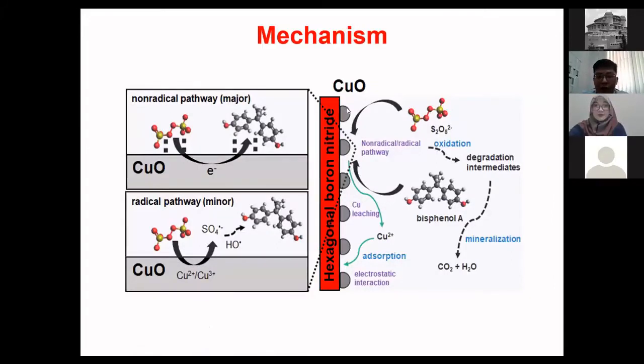You have the copper oxide, right? And then you have this support, boron nitride. And when you have activation process through non-radical and radical pathway, right? Then you have some reactive species generated to attack the pollutant. And what is interesting is that the copper leached out, right, will be reabsorbed back on the boron nitride. And after adsorption, you can take this catalyst, you calcine it at about 300 to 400 degrees Celsius, and then this adsorbed copper can turn back into copper oxide. So that means you are not losing any copper.